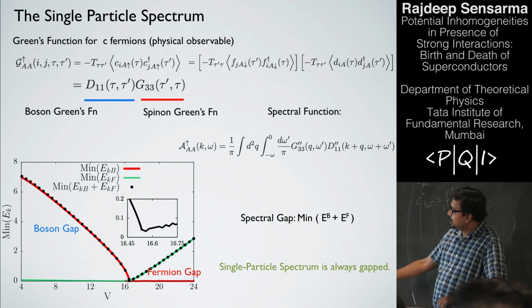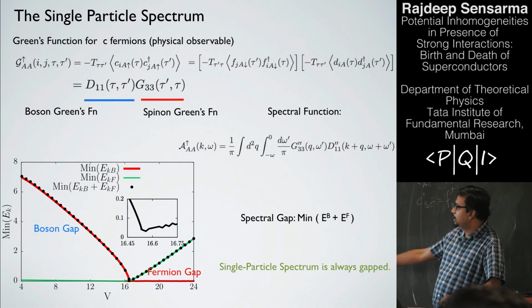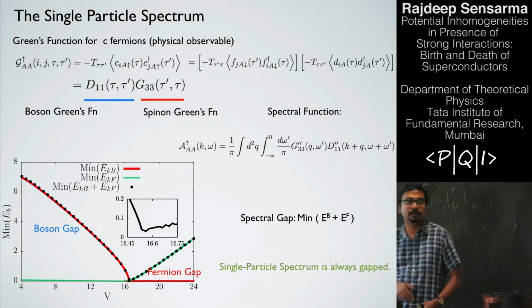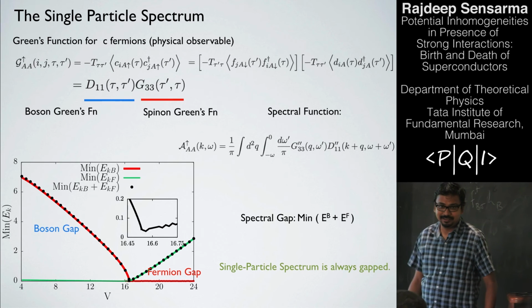It's like a mass. The mass of the bosons vanishes at some point, and then they remain 0 in the superfluid, superconducting phase. Here the fermionic gap is order J. You can't really see it because it's order J, but here it kind of takes off. So basically the total gap looks like this. Here it is dominated by the boson gap, here it's dominated by the fermion gap, here the spinon gap, and in between, as I showed you, it doesn't really go to 0 because it gets preempted by a first order transition.